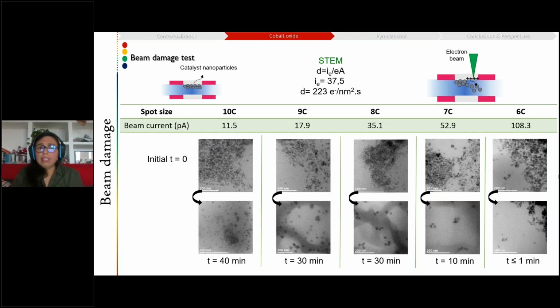We tested different spot sizes. What we observe is that, depending on the spot size that you use, of course, you will have better or worse resolution. But also, prior to any beam-induced transformation, the particle will detach because of the accumulation of charges at the surface of the observation window. So in our case, in particular, they won't degrade because of the beam, but they will go away from the window.